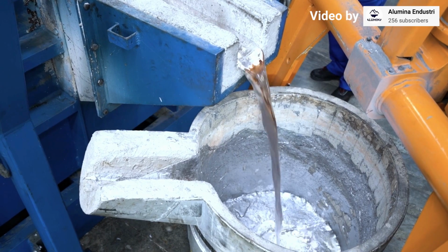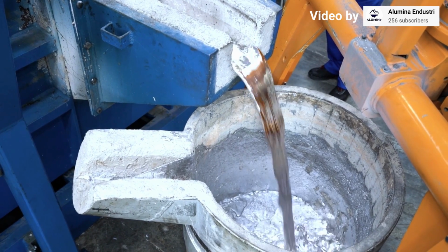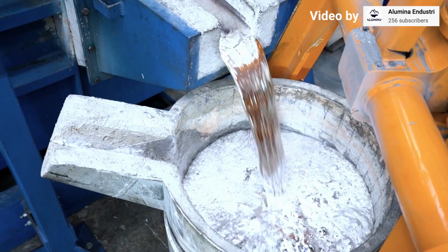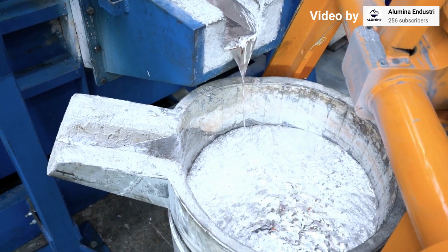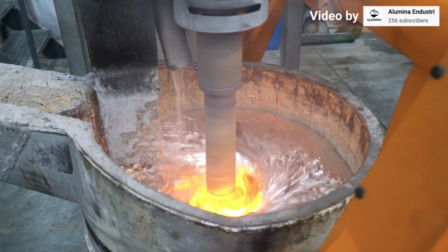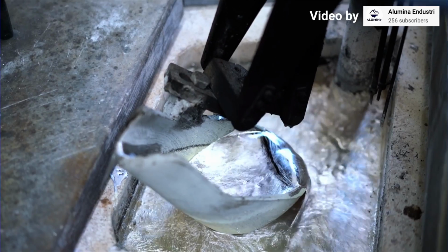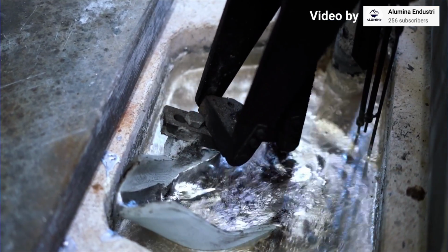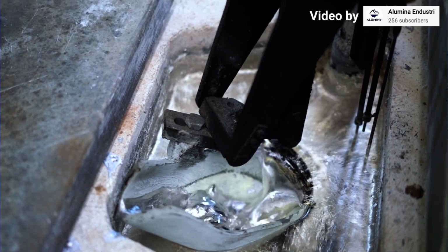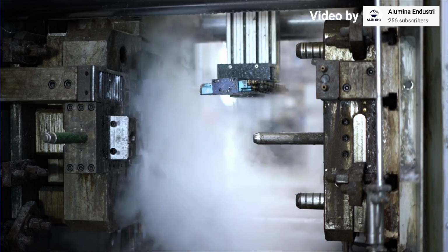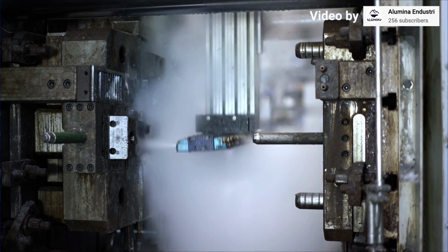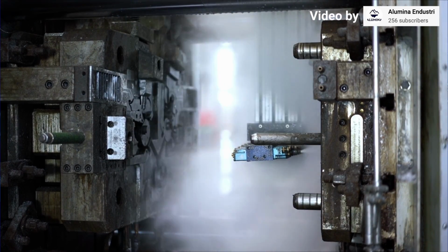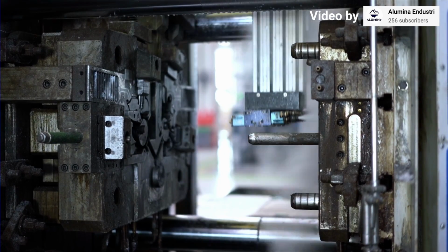The key reason why the fill time is so short is that as soon as that molten aluminium touches the relatively cold die at around 150 to 200 C, it immediately freezes. To give you an idea, a die wall will increase in temperature to around 400 to 450 degrees centigrade in about 1 second as the heat is transferred from the aluminium into the die, and then needs a further 20 seconds to cool back down. Now that's violent.